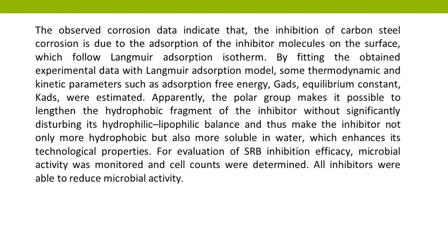The observed corrosion data indicate that the inhibition of carbon steel corrosion is due to the adsorption of the inhibitor molecules on the surface, which follows the Langmuir adsorption isotherm. By fitting the obtained experimental data with the Langmuir adsorption model, some thermodynamic and kinetic parameters such as adsorption free energy, ΔG_ads, and equilibrium constant, K_ads, were estimated.